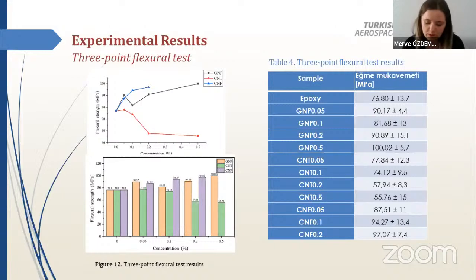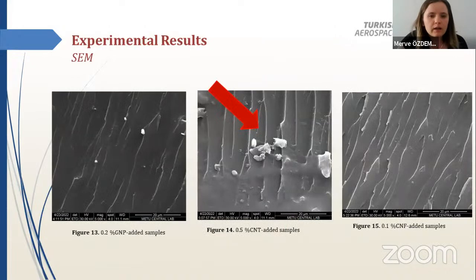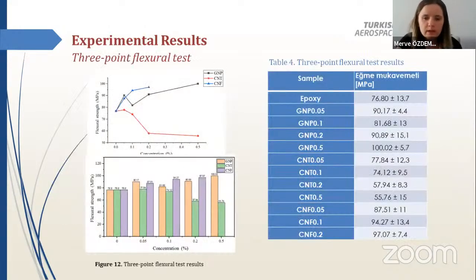1.35% compared to the resin. It is seen that the flexural strength values decrease as the CNT content increases. This situation reveals that the CNT and the resin were not mixed homogeneously enough, and agglomerations occur due to weak interaction between them. This weak interaction was also confirmed by SEM images. Finally, when the effect of CNF addition on flexural strength was examined, it was observed that the flexural strength values increased as the CNF content increased.